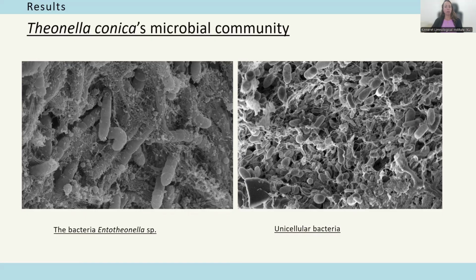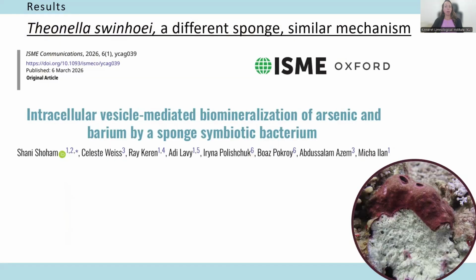This was important because Theonella swinhoei, a closely related sponge, is also known to accumulate metals such as arsenic and barium through processes associated with a similar symbiont, Entotheonella. Therefore, we ask whether the microbial community of Theonella conica differs from Theonella swinhoei and whether Entotheonella might also be connected to molybdenum accumulation. To make the story short, it's not the same bacteria, but it's from the same genus.